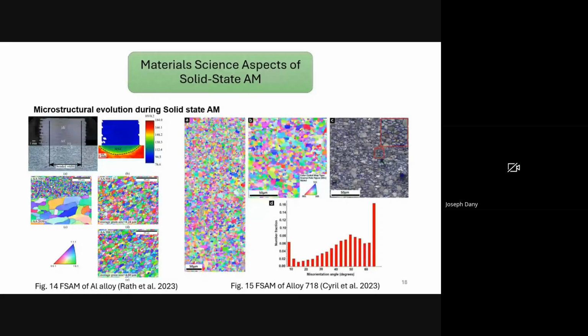The microstructure development produced by dynamic recrystallization has direct consequences for properties. The finer recrystallized grain size increases strength by the Hall-Petch effect. It can improve toughness and fatigue resistance, and tends to randomize or weaken the strong rolling textures of the substrate. The final grain size and boundary character, however, depend on processing variables, that is tool rotation speed, traverse speed, heat input and number of passes, and alloy features, solute content and precipitate particle population. Excessive heat or prolonged thermal exposure after dynamic recrystallization can cause grain growth and partially erase the refinement. So process control is essential to retain the fine recrystallized microstructure, as we see in the EBSD maps.